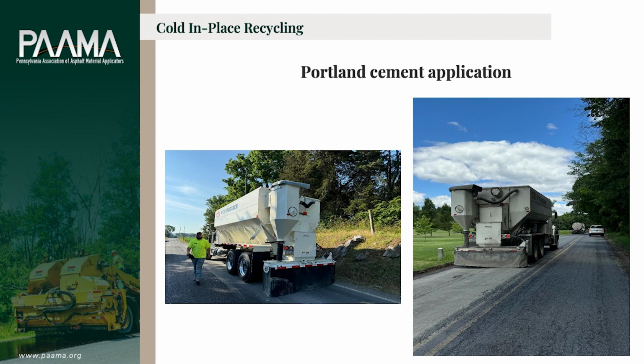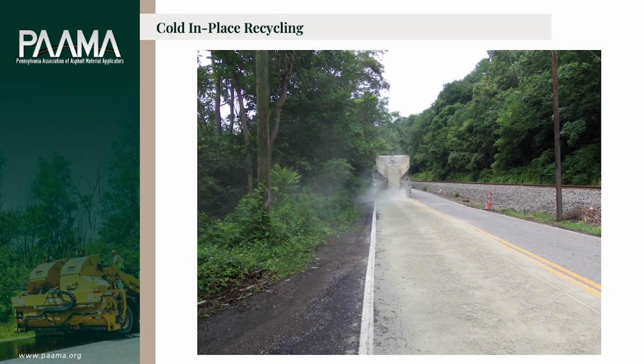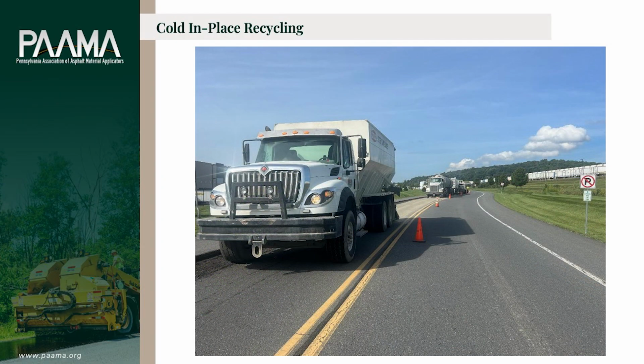You want to put the Portland cement down with an automated machine. These machines are all calibrated. And you can see the small amount of cement that is laid on the roadway. One thing you don't want to do, although that's very thin laid on top, 5 pounds a square yard, you do not want any of the public driving through there with their car. That is so light it will get airborne. And you'll have a dust cloud, a fog cloud there, and the car will be covered in cement. So we have to make sure that our traffic control does not allow anybody to drive into that dry product. Here you can see very close proximity from the recycle train, that tanker behind, and the actual applicator for the cement.